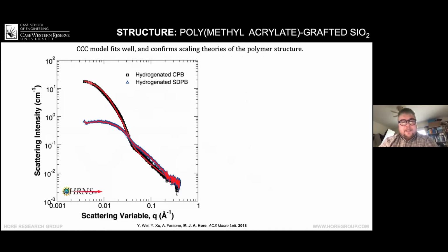So here's our data, and you can see that although these samples are very similar, the scattering from them is actually quite distinct here. So this sample here has the hydrogenated inner block, and then the deuterated outer block. This sample in blue here has the opposite deuteration scheme. And hopefully what you can notice is that the model that I just described to you in red fits the data quite well. And again, we can narrow down the parameters that we use here.